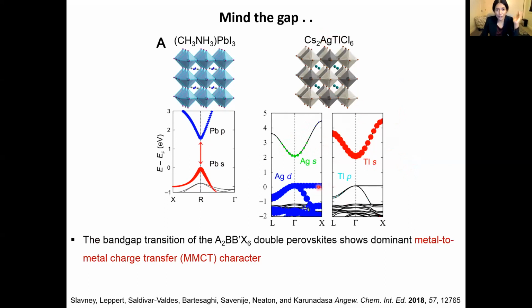Because I want to show you the individual metal contributions. So I see that if I look at the valence band, it has mostly silver character. There's practically no thallium character. And if I look at the conduction band, it has mostly thallium character. In other words, if I look at the band gap transition, it is an electron moving from silver to thallium. It's a metal-to-metal charge transfer.